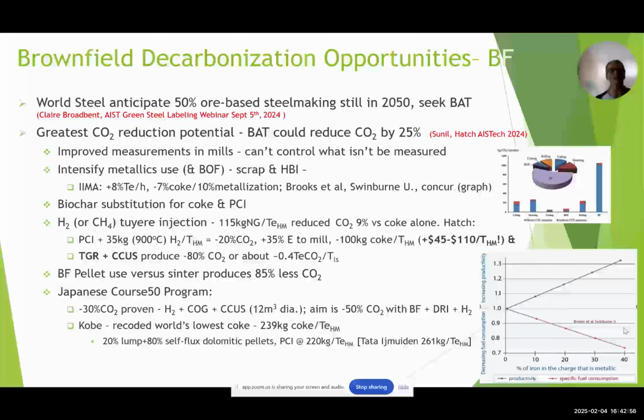Hatch, on the other hand, has said that PCI plus 35 kilograms of 900 degrees C hydrogen can give you a 20% reduction in CO2, but also energy to the mill and 100 kilograms of coke reduction, but it's expensive. If you add top gas recycling and CCUs to this, you can produce an 80% reduction in CO2, which will bring it down to 0.4, which is close to that of an EAF with 100% scrap.